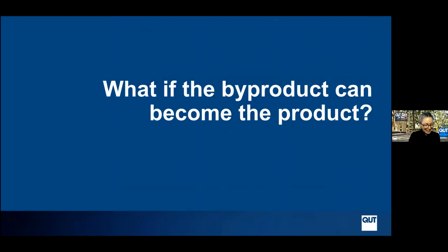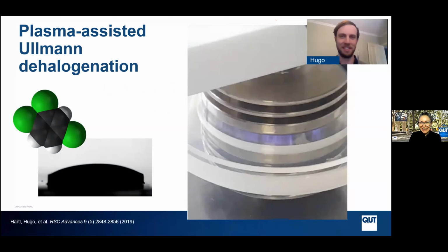So this is where we take another little foray into a slightly different direction. What if the byproduct could become the product? This is work that's being done, again, in a film growth sort of way. And this is Hugo Hartl, who's been working with atmospheric pressure cold plasma for a few years now. What's shown here at right is a dielectric barrier discharge plasma apparatus, and the purple part there is the plasma. So we're interested here in the same reaction, Ullmann dehalogenation. And what we've been working with is a liquid at room temperature molecule. This is 1,2,4-trichlorobenzene. And what Hugo does is to put it in a droplet onto a surface and then to put it into the dielectric barrier discharge plasma.